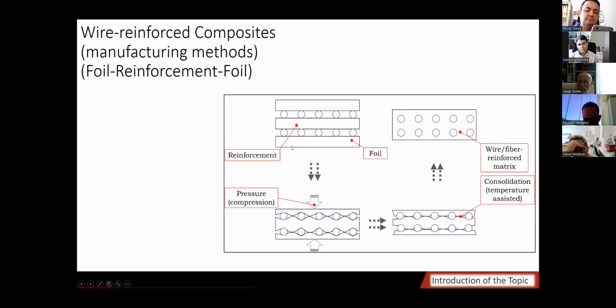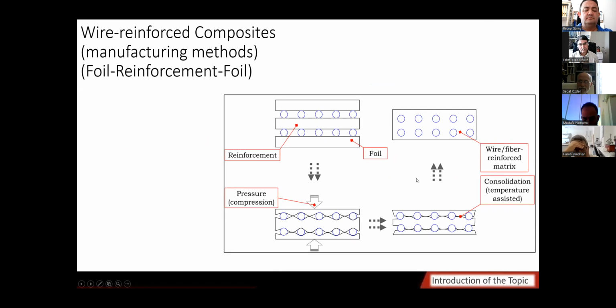Here's another technique which is also used for wire reinforced composites. You take foils and you put the reinforcement between the foils, you compress them, you put them at elevated temperature, and then you wait there. Eventually, at these areas of the foils, temperature assisted bonding occurs, and eventually this structure is acquired. This structure is similar to this one, but these two techniques are the ones which I have come across, in which some studies have reported the manufacturing of wire reinforced composites.